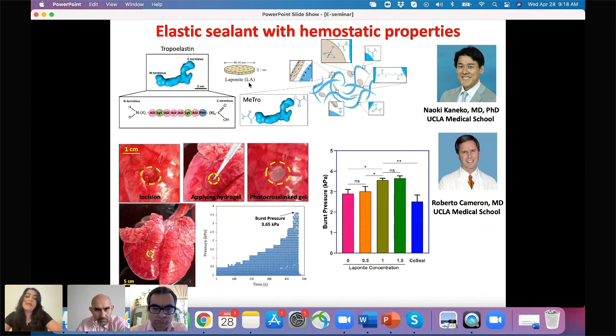And then we combine it with nanoparticles. These are laponite nanoparticles that are negatively charged, and they can form electrostatic interaction with Metro. Once we combine them together, we can polymerize them the same way that we did for Metro on the defect site. And then these laponite nanoparticles can cause blood coagulation on the defect site. Therefore, it can stop bleeding once we apply the biomaterials.